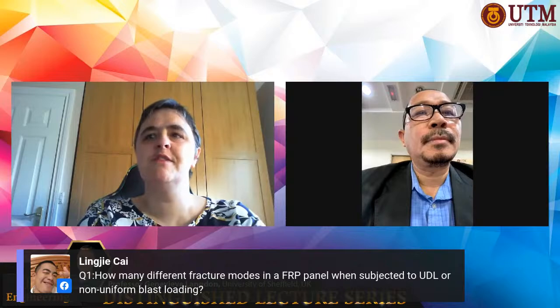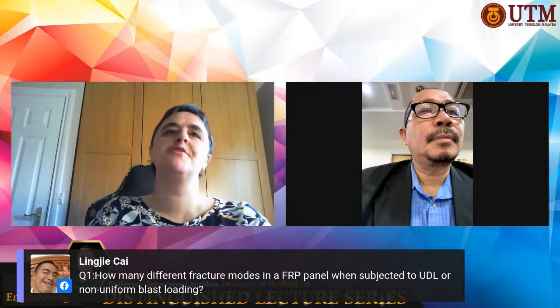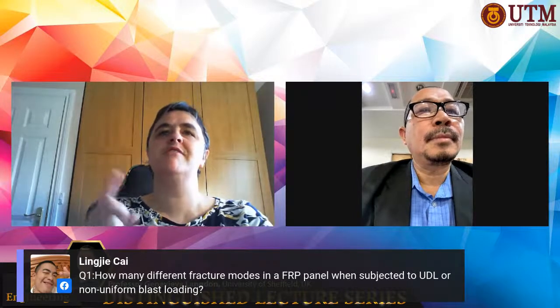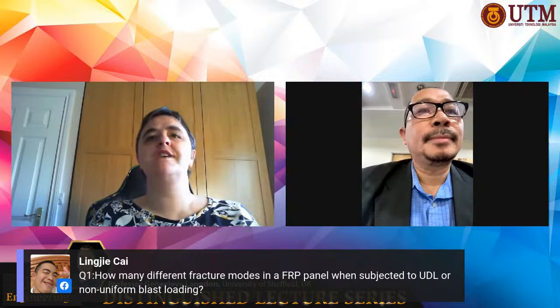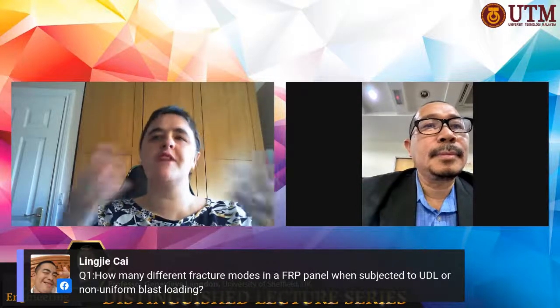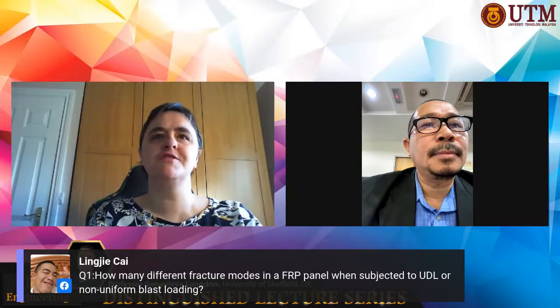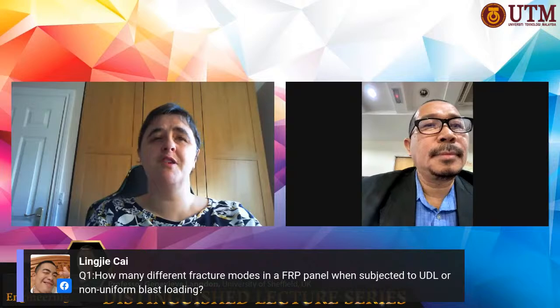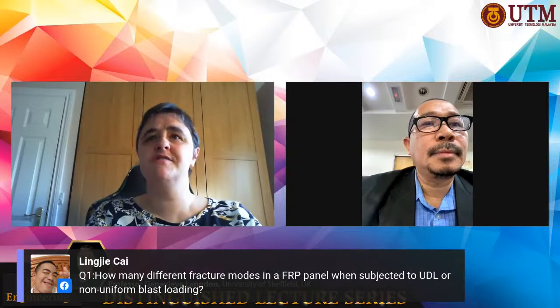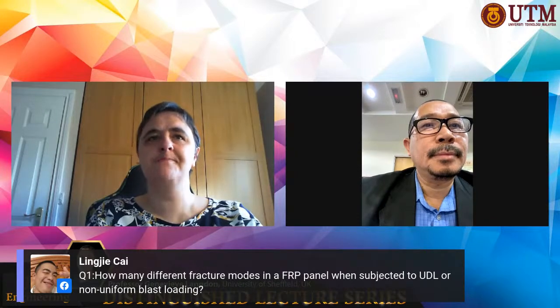And this would be true in a metal panel as well. If you load it in the center, you're going to get a cap that flies out due to shearing around the edge of the loading. Whereas if you load it uniformly, it's going to fail at the boundaries because that's the place where it's being stopped from moving. In a fiber-reinforced polymer, you've got all of that, but much more complex because you've got all these other additional failure modes. And you've got the fact that fiber-reinforced polymer is probably weaker in shear than a material such as steel or aluminium.